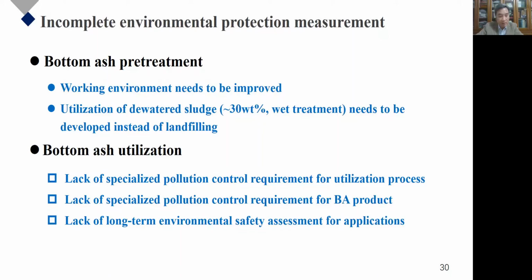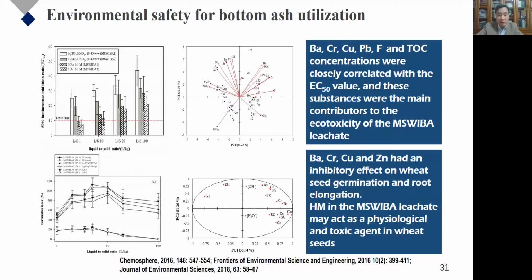For the utilization of bottom ash products, specialized pollution control standards are lacking for the process, as well as for the product considering different application scenarios, as mentioned before. By now, we still have no standards and guidelines on environmental impacts and risk assessment for beneficial utilization of bottom ash. Is it safe for utilization in the long term? Further lab and field studies need to be carried out. For example, our lab investigated the ecotoxicity and phytotoxicity of bottom ash leachate and found some relationship between heavy metals as well as TOC leaching and the toxicity value, indicating that the sustainability of existing technologies for bottom ash treatment, utilization, and disposal needs further long-term assessment.